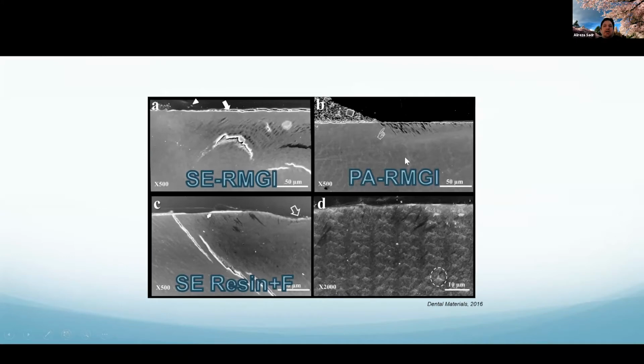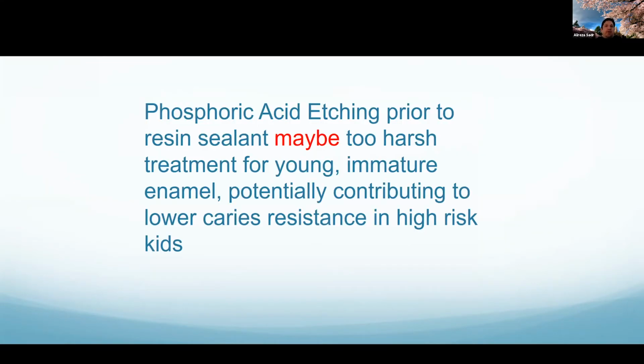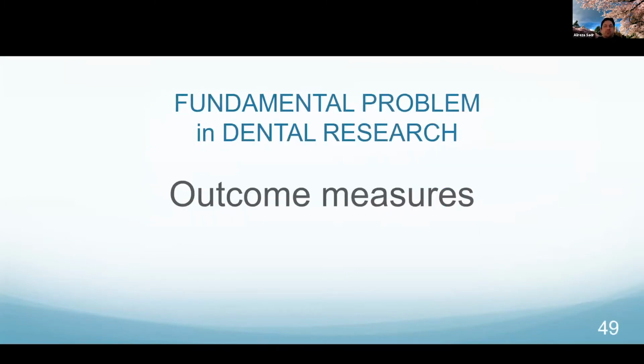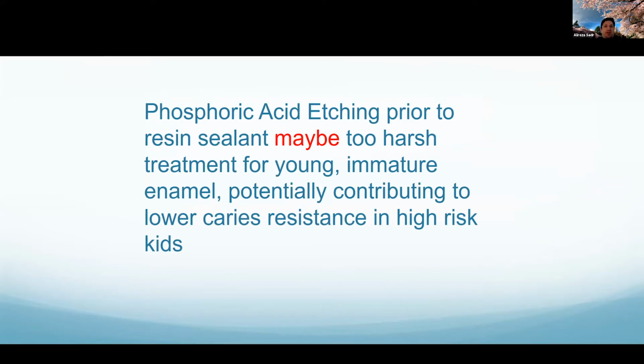Okay, and here's what we see under the microscope. If you look at the phosphoric acid etched enamel, we're creating a say couple of micrometer deep zone of demineralization, right? And when we subjected these samples to a caries model, this is where we got some caries formation. Okay, I know it's a little bit too much, but that's what we found in the lab. So polyacrylic acid etching for glass ionomer sounds to be not a bad idea, followed by air abrasion for sealants. Okay, so it might be a too harsh treatment, especially when it's young and immature enamel, right?